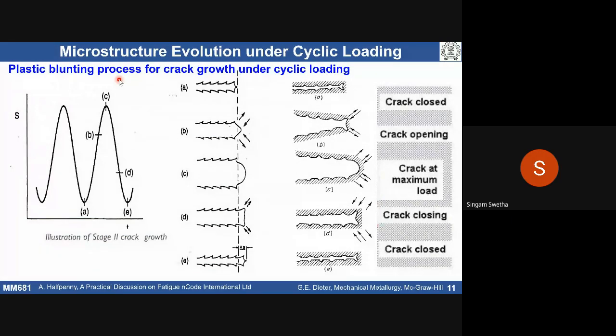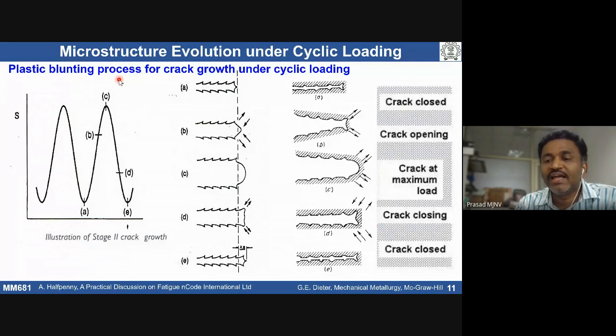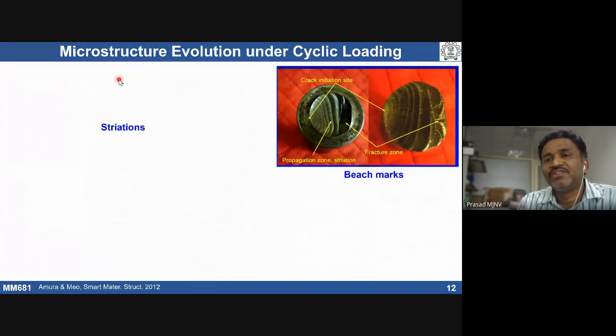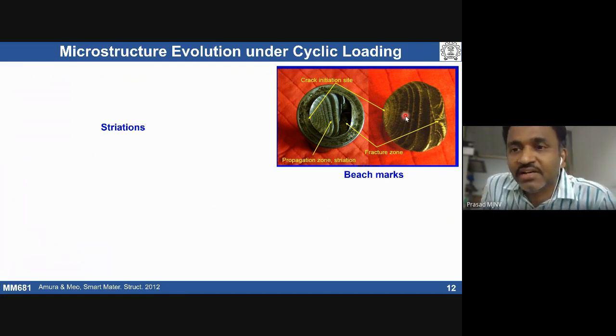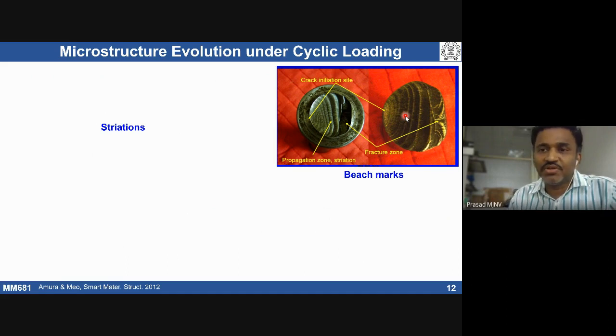So this crack propagation can lead to certain microstructural features. For example, you have taken a component which has failed. If you see the formation of this kind of beach marks, this is an indication that the material has undergone cyclic loading conditions. The component was actually subjected to cyclic deformation.